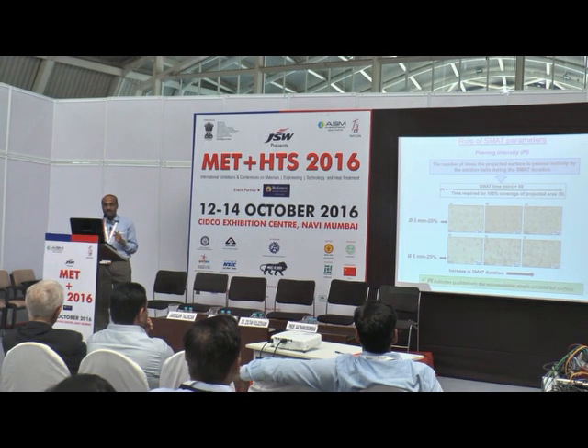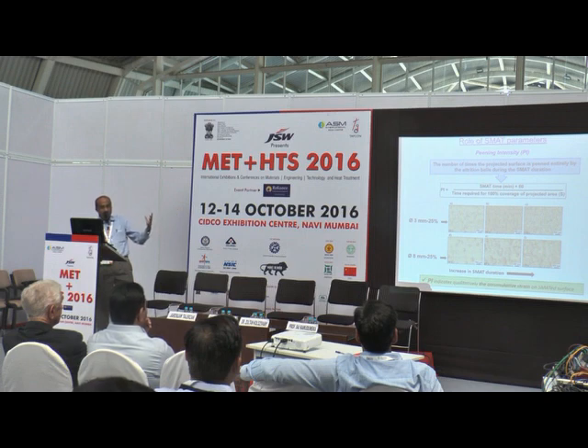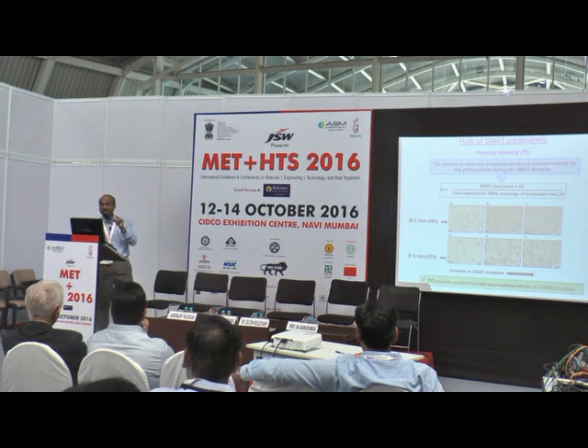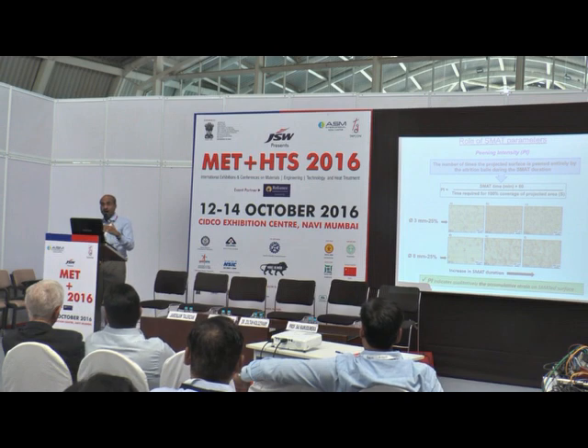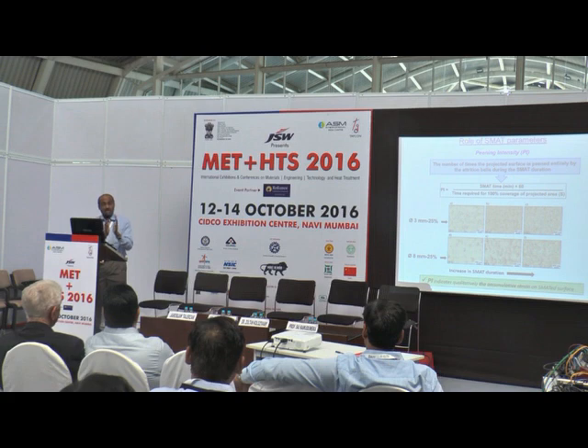So peening intensity, what does that mean? Consider the specimen surface. Initially it was like this, for example figure A. How much time is required to cover the entire surface with the indentation marks, which are shown here? These spherical marks are nothing but deformation regions observed on the specimen surface. So this time required to cover the entire surface, divided by the SMAT duration, gives the term called peening intensity. That means peening intensity tells you how many times your surface is impacted by balls during a SMAT duration.